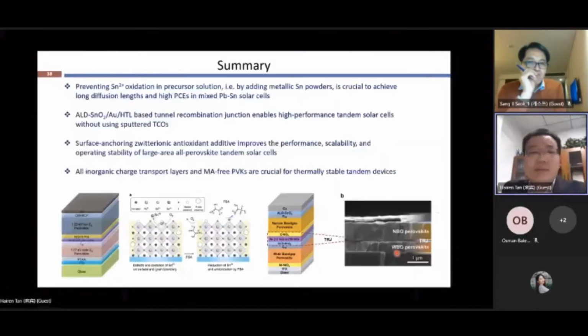So at the end, I will briefly summarize what we have talked about here. The first is that we have to prevent tin oxidation in the precursor solution. What we can do is add metallic tin powder or other reducing agents to the precursor solution. This is very crucial to achieve long diffusion lengths and high efficiency in the solar cells. We also developed a tunnel recombination junction that is free of sputtered ITO, and this can also give us very high performance tandem devices.